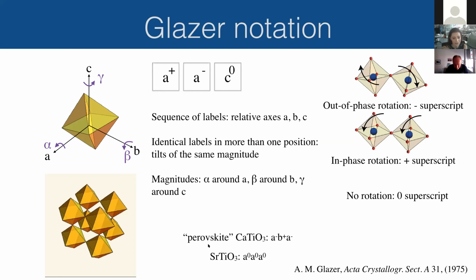So as an example, I just put perovskite. So this means the perovskite. This is the mineral perovskite that you can go and mine if you want to in Siberia. Annoyingly, the mineral perovskite is not a perfect perovskite. It's not an archetypal one. It has distortions of this type where you have equivalent magnitude rotations that are out of phase around the A and C axes. And in the B axis, you have in-phase rotations. Now, the archetypal perovskite, which is not perovskite, but it's perovskite-like, of course, is strontium titanate. At room temperature, it has no rotations around any of its axes, so you can just call it A0, A0, A0, alpha equals beta equals gamma equals 0 degrees.